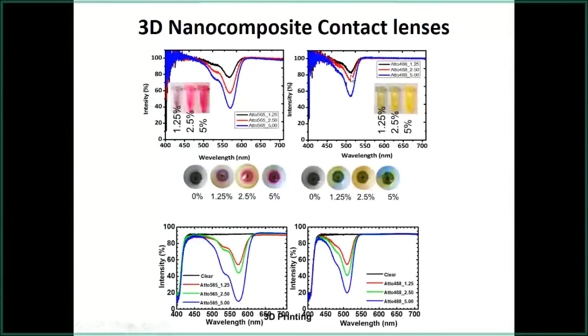So the dip of this dye should have been at 488, over here sort of, but it has moved over here, beyond 500 nanometers. So this is a challenge, that even before 3D printing, during the fabrication of the resin, the dyes change their optical properties. And sometimes for some materials after 3D printing, the optical properties also move. After the UV exposure, we sometimes observe that the optical properties of the dyes or the resin have changed as well.